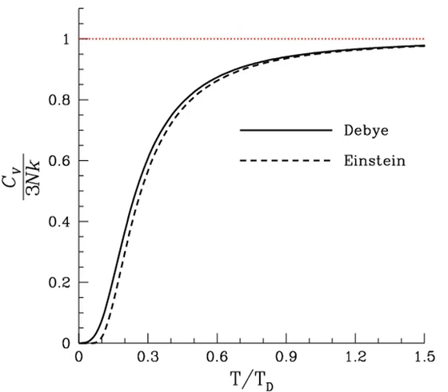Paraffin, for example, has very large molecules and thus a high heat capacity per mole, but as a substance it does not have remarkable heat capacity in terms of volume, mass, or atom mole, which is just 1.41 R per mole of atoms, or less than half of most solids, in terms of heat capacity per atom. In the last column, major departures of solids at standard temperatures from the Dulong-Petit law value of 3 R are usually due to low atomic weight plus high bond strength, as in diamond, causing some vibration modes to have too much energy to be available to store thermal energy at the measured temperature.